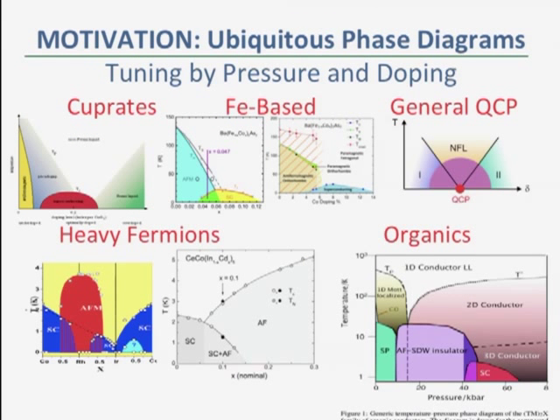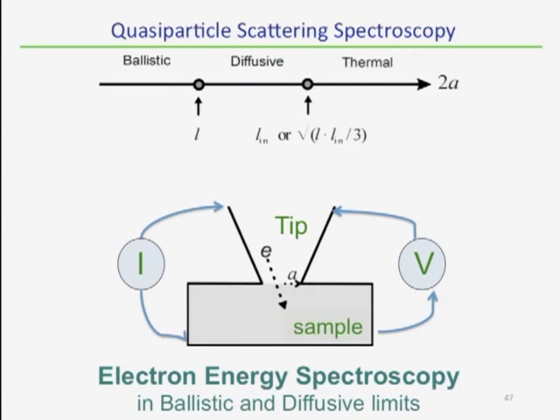And I'm going to end up with 2 minutes here. Okay, this is 1 minute of my own research. So as I mentioned, there's a ubiquitous phase diagram. This is the line that we added here. Our measurement is point contact spectroscopy, where we inject electrons into a material and measure the scattering. This has been used for many years to look at phonon scattering, magnon scattering, even Kondo scattering. And it's been looked at Andreev scattering, where you look at reflection, which is understood because we understand the BCS theory of superconductivity.